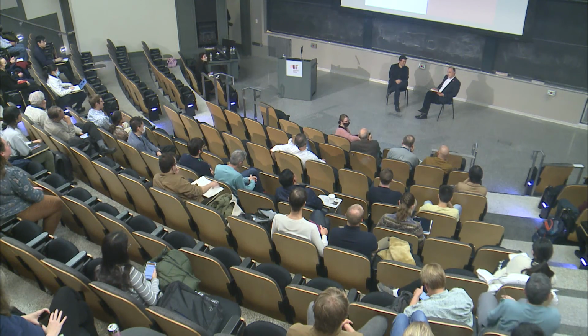Thank you. If I may add to that question, on the ferroelectric demonstration, what's the domain size? How small can the memory bit be if this is what you choose to do? Yeah, so we don't know yet what's the minimum feature size that we'll maintain, but we actually know quite well that it's based on this sliding on this domain wall. In principle, you can pattern the parallel stack down to 5 nanometers by 5 nanometers, 10 by 10. It should work, down to very, very small sizes. And then the question is just how much current would you choose to pass to probe it? Well, again, you control it with an electric field.